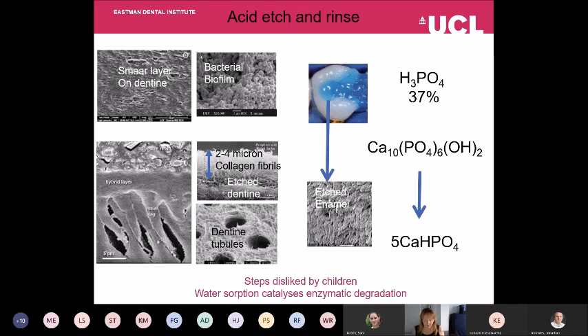Once you've drilled the tooth structure, what you have left on the surface is what's called a smear layer that's contaminated with bacteria. If you treat that with the phosphoric acid gel, that will kill the bacteria, but it also etches the enamel, producing a rough surface that is relatively easy to bond to.